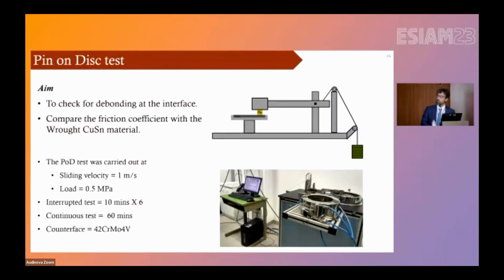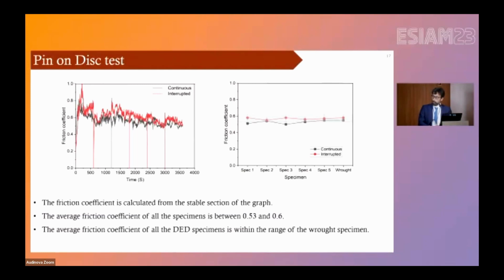And we performed pin-on-disc tests in dry condition. So why do this? We want to simulate a worst-case scenario, typical of startup of the gear, in which we have a poor lubrication condition, and so we have high friction. And we wanted to evaluate the dry friction coefficient and the possible delamination of the coating from the substrate due to poor adhesion at the interface. Okay, so the friction coefficient turned out to be comparable to that of the wrought bronze counterpart, no significant difference. And in addition, we observe no delamination of the coating from the substrate.